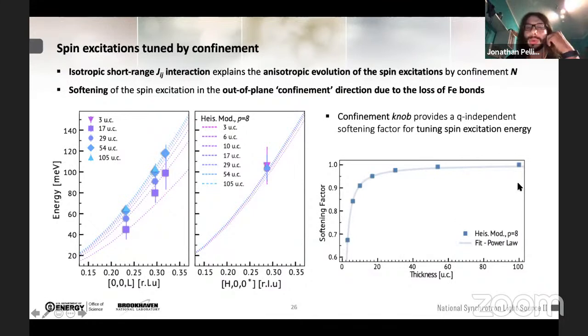And we observed that this calculation actually follows a power law, which can be used in principle as a calibration and can be used in material synthesis in order to tune the spin excitation energy. And this is something that is particularly appealing in fields such as spintronics and magnonics, where the community is looking for materials that have a tunable spin excitation energy.